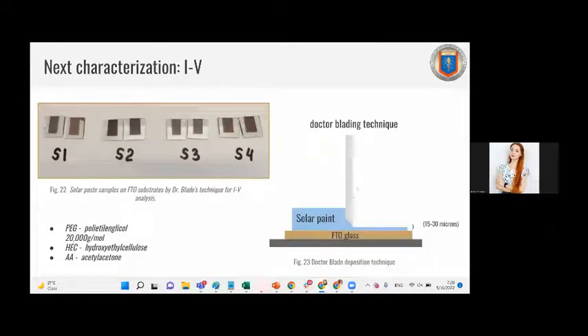And the next pending characterization is the intensity current test. This is to get to know the efficiency of the photovoltaic material. For this, the samples were mixed with polyethylene glycol, hydroxyethyl cellulose, and acetylacetone in order to form a paste, because initially they were in powder form. And then thin films of this paste were applied on FTO glass through the Doctor Blade technique. You can see the samples already prepared.